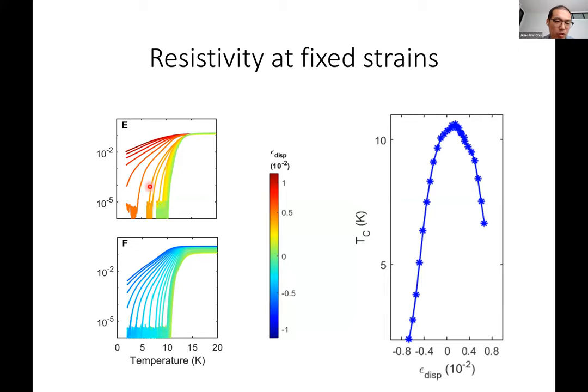let's first define, for example, the zero resistance state as TC, and then plot this TC as a function of strain. Then you can see that this superconducting phase boundary is actually forming a dome shape, where the peak of the dome is at the center, at the zero strain state. Once you plot this, initially you have a rather flat response to strain, but once you pass a certain strain, then this TC drops very significantly as a function of strain.